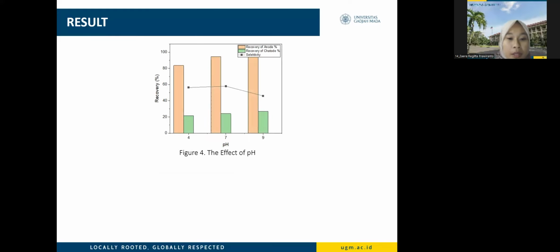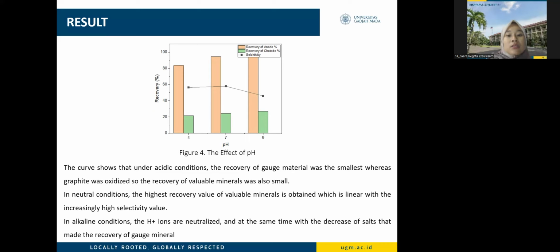And for pH condition, it shows that under acidic condition, the recovery of gangue material was the smallest because the H plus ions dissociated and made salt from the reaction with the cathode, whereas graphite was oxidized, so the recovery of valuable mineral was also small. In neutral condition, the highest recovery value of valuable mineral is obtained, along with a high selectivity value. In alkaline condition, the H plus ions are neutralized, and at the same time, the decrease of salt made the recovery of mineral increase.